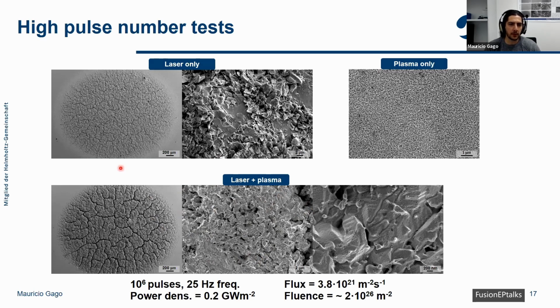But still, this is very important because one of the plans to mitigate the effect of ELMs is by ELM pacing, which means that ELMs will actually be happening more often, at a higher frequency than for unmitigated ELMs, but they will have a lower power load. And so if they deposit a lower energy per ELM, this gives time for the material and for the cooling system to dissipate the heat, and then the material will not remain at higher temperatures that much.